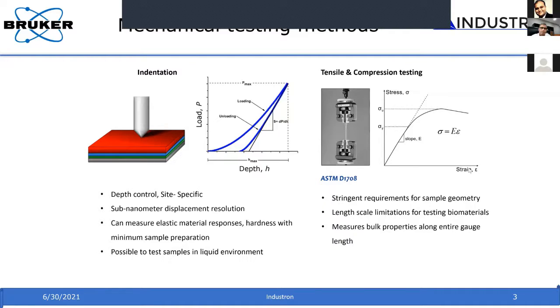When you get this load displacement curve, you can analyze the curve. For example, the unloading curve you can analyze by measuring the stiffness. If you take the load divided by the depth, that gives you the stiffness. So you fit the unloading curve and measure the stiffness. And once you have the stiffness measured, from that, you can measure the hardness and modulus by modeling. Okay.